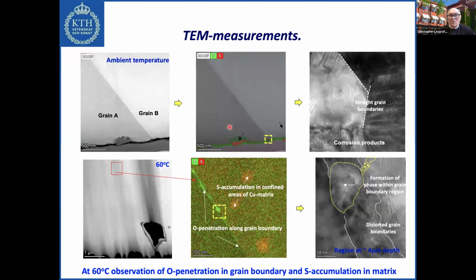But we want to have more information, and for this reason we have taken the same sample as I showed before with the FIB, focused ion beam sample, but now we look at the microstructure along the same grain boundaries as we looked before. And you can see here now, this is at ambient temperature again, grain A, grain B. Now the corrosion products are down here, but it's basically the same area we look at.